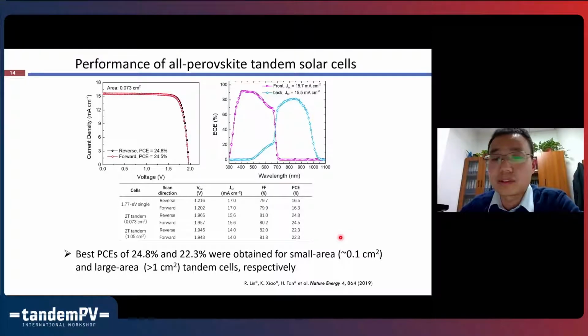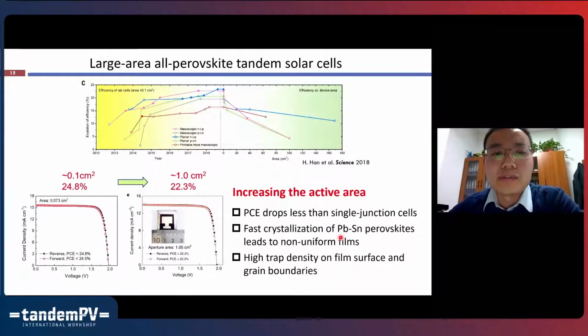because in the field of perovskite photovoltaics, one big challenge is that we typically observe a quite fast drop of the efficiency when we increase the area beyond 1 centimeter square. As we can also see in our tandem devices, although we found it's quite an interesting phenomenon that for all perovskite tandem devices, the PCE drop is usually less than for single junction devices, still the efficiency drops by 2.5% absolute when we only increase the area from 0.1 centimeter square to 1 centimeter square.